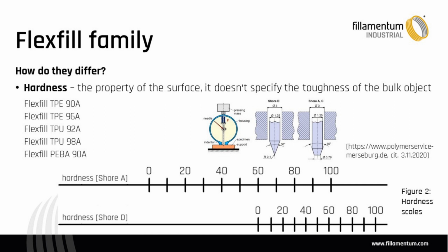Now I will talk about hardness. It is quite important to mention it because there is the list of our flexible polymers. We can see that Flexfill is the flexible filament. Then we named it according to the chemical structure, TPE, TPU and PEBA, and the third part of the name is the hardness. It's 90, 92, 96, 98 Shore A. So it is really important to understand that hardness doesn't tell me anything about the bulk mechanical properties. It just tells me how hard the surface is. It's the property of the surface. So when you say that you need a harder material, it's usually that you need a tougher or stiffer material.